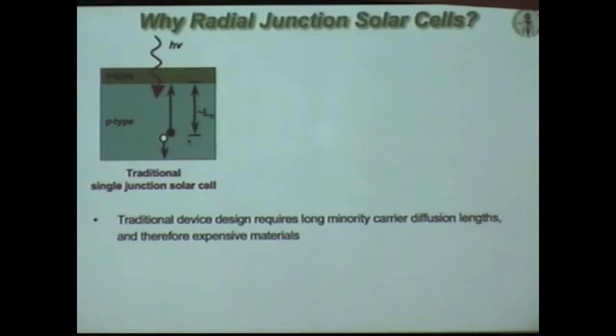The rods are important because planar solar cells, in a design from Bell Labs back in the 1950s, have an important physical constraint. You need 300 microns of silicon, for instance, to absorb sunlight. That's the absorption depth in silicon. Any less wastes sunlight by letting it through, any more wastes silicon. So you can grow 300 microns of a crystal of silicon, but it has to be very pure, because for the light that's absorbed very deeply, the excited state created has to last back 300 microns to get back to the space-charge region in the wires to lead to current.